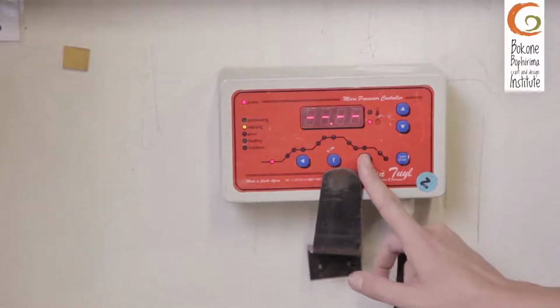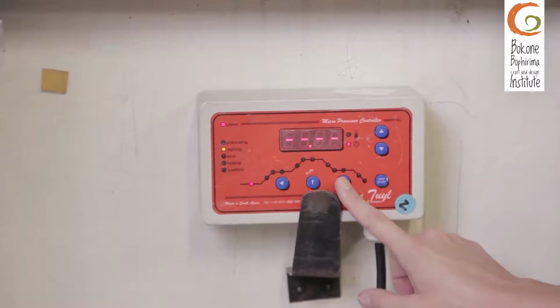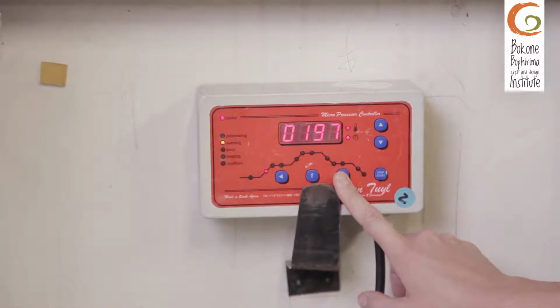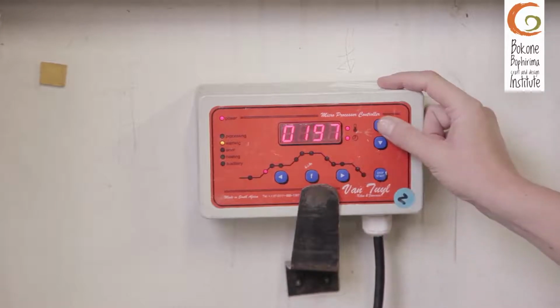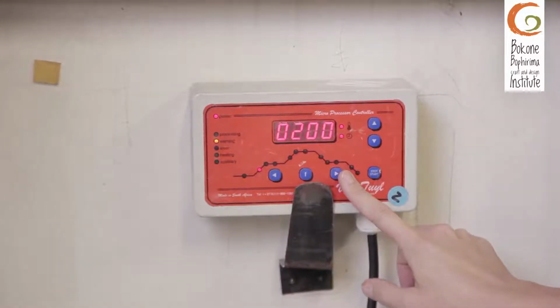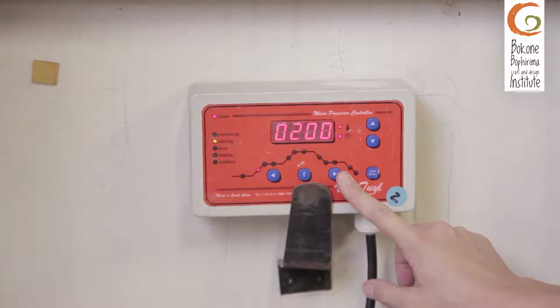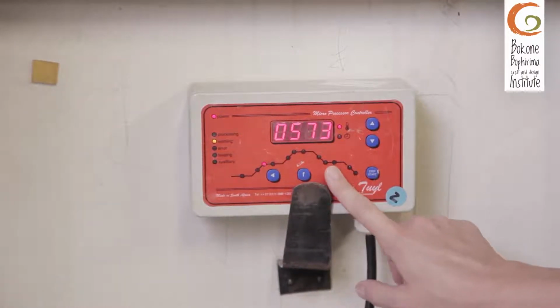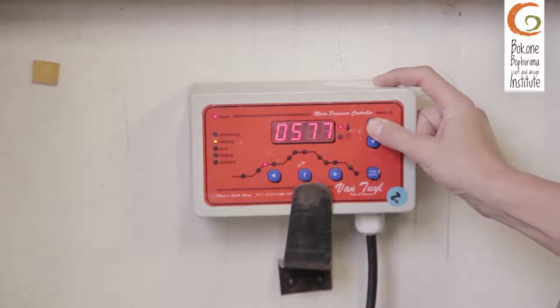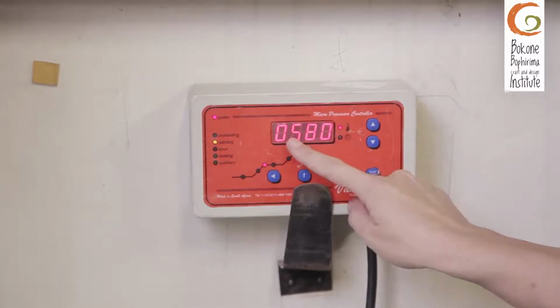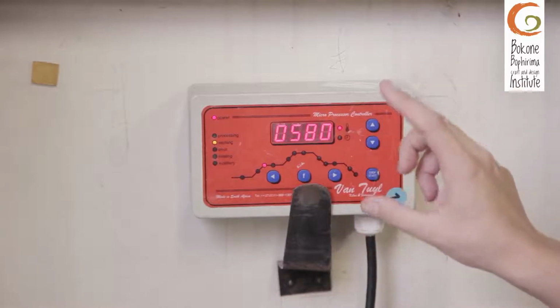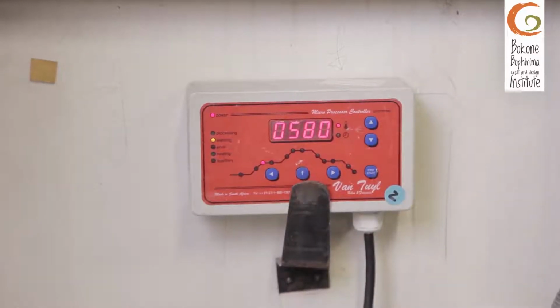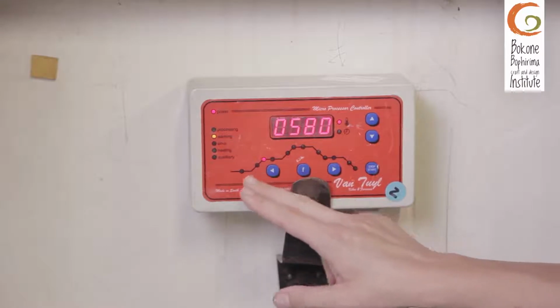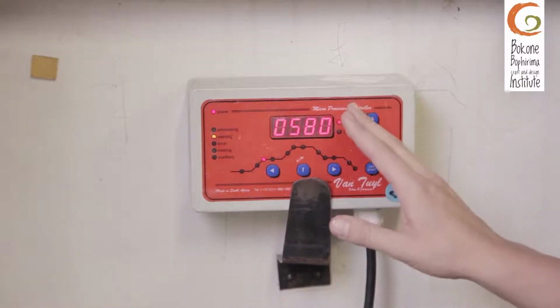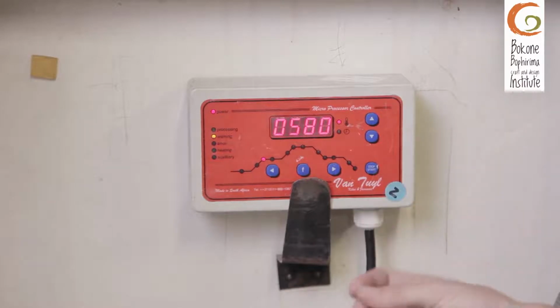We are not using a delay because we want our kiln to start firing immediately. And here we are going to take our glass up 200 degrees an hour. I'm taking it up not too fast because I'm fusing two pieces of glass together, so I want to ensure that it goes slowly here. And then taking it to the temperature point where my glass is the most fragile. I'm then taking it up to 580 because from 580 to room temperature, my glass is fragile. So I need to work with this process very slowly.